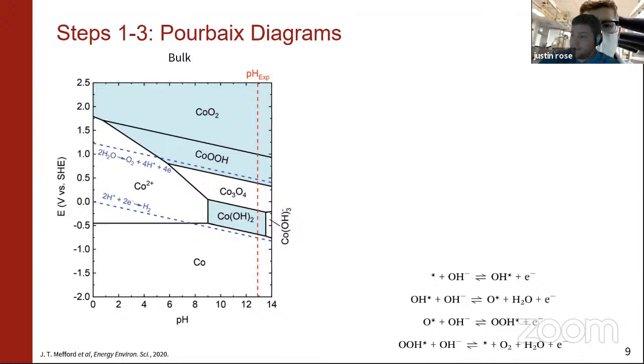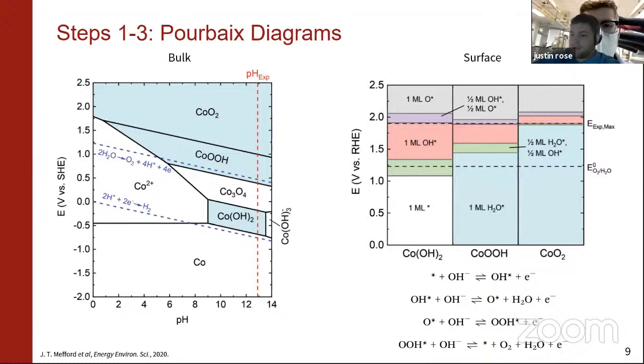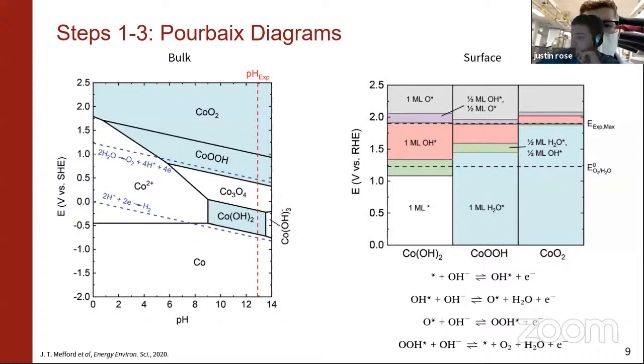They left out the Co₃O₄ compound because it has a very different crystal structure from the other three phases, meaning it's likely very kinetically limited for the electrode to actually transform into that phase. Additionally, the characterization paper had found reason to believe this phase did not play a role in the oxygen evolution reaction. With this knowledge, they take the three phases of interest and start simulating coverage conditions. On the y-axis is potential; on the x-axis is which bulk species it corresponds to.